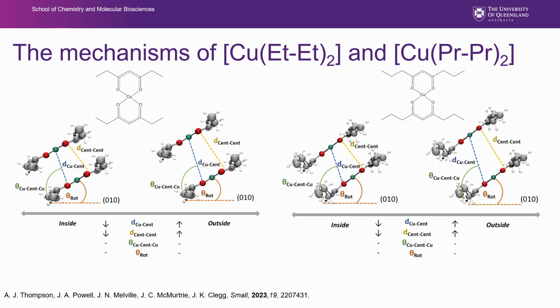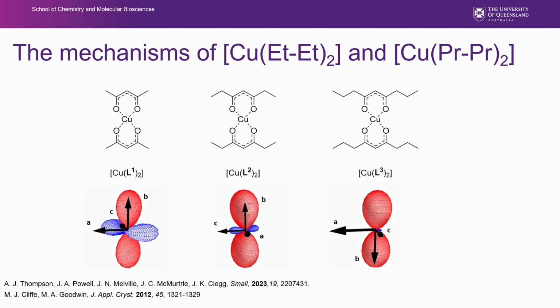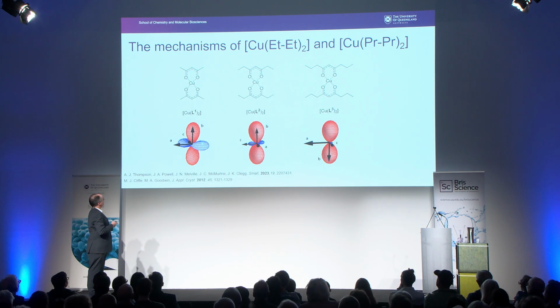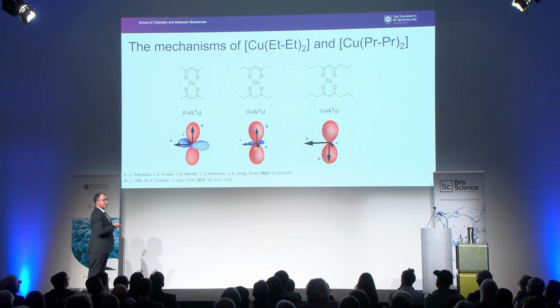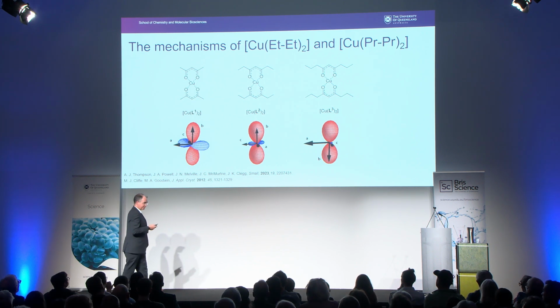And this is because the intermolecular interactions are fundamentally different. But we're still getting changes to occur on the molecular level. Just to highlight how they're different, these are the same things but plotted out in 3 dimensions. So here was our first copper ACAC, where the B-axis was changing the most, and we had an elongation in the A-axis, whereas in these other two, we're getting very different effects just in the shapes of how they're working.